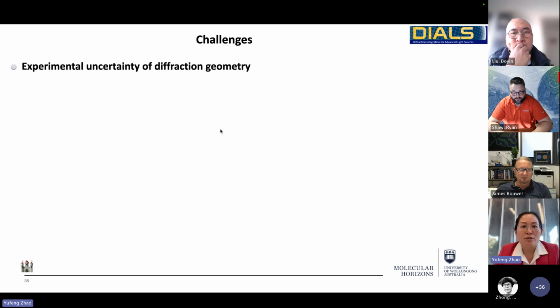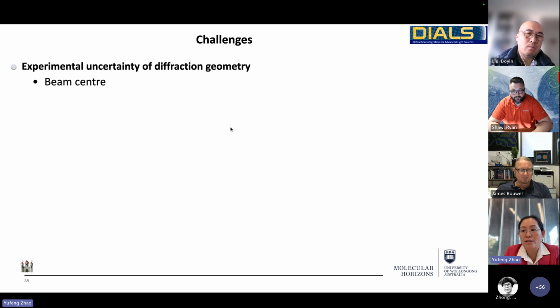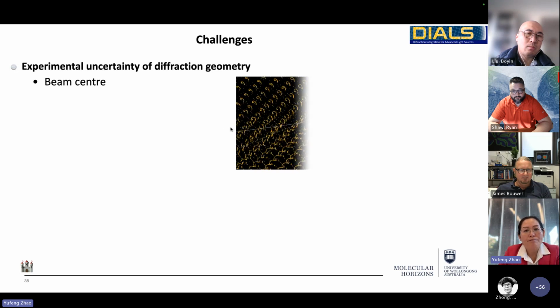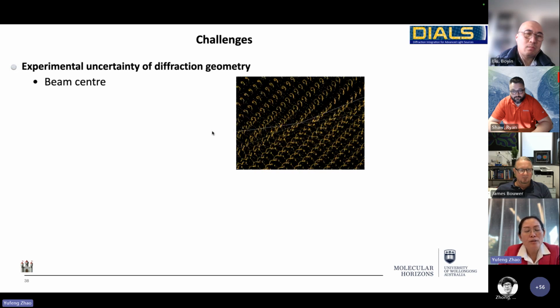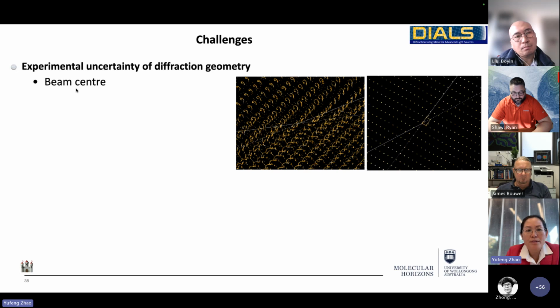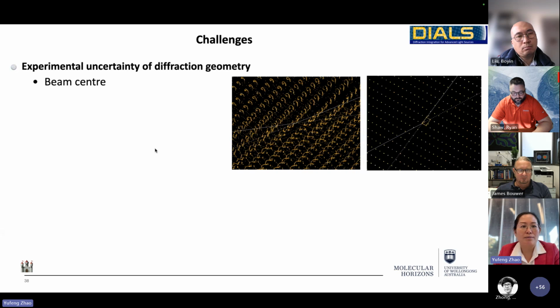Now I would like to summarize some challenges. The main challenge is the uncertainty of diffraction geometry. There are many factors that impact the diffraction geometry, for example, the beam center. In this one the beam center is not correct and you see the reciprocal lattice distorted. The right side one is correct, with a very accurate beam center, and we get nicely lined up dots.